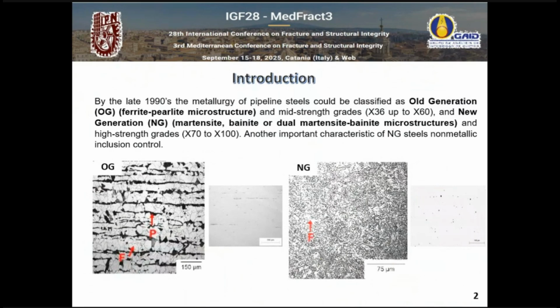And the microstructure, well, it looks like quench and temper, but it's not quench and temper. It is produced by controlled rolling processes. They call it thermomechanical processing. So that gives us, in addition to a very fine-grained microstructure, also the reinforcing second phase, which is basically bainite and martensite.